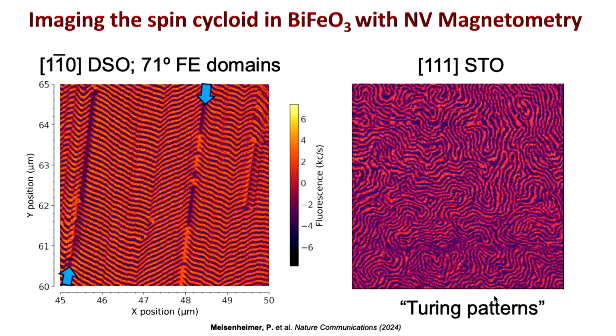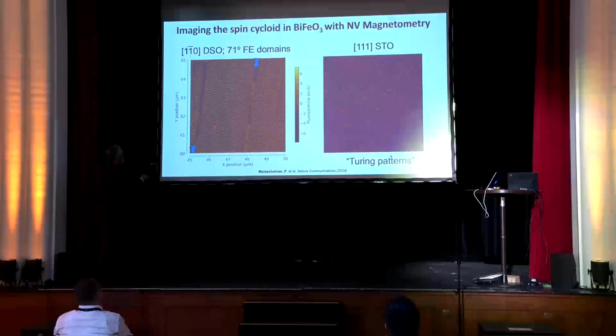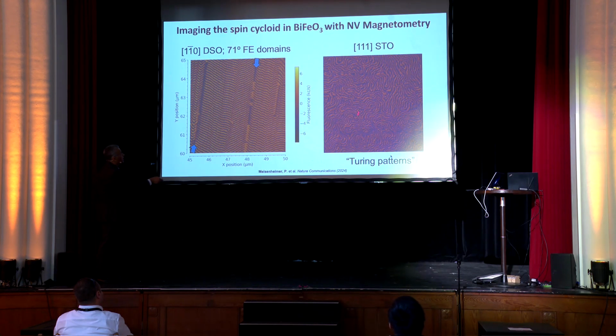These are images of the spin cycloid in bismuth ferrite, where you have an array of 71-degree ferroelectric domains, and you can see it forms beautiful ordered structures of the spin cycloid. You can start to see defects in the spin cycloid. You can start to see dislocations. If I now grow this on a 1-1-1 surface, where the polarization vector is coming out of the plane, then you can start to see what we call Turing patterns. These are the spiraling patterns of the spin cycloid.